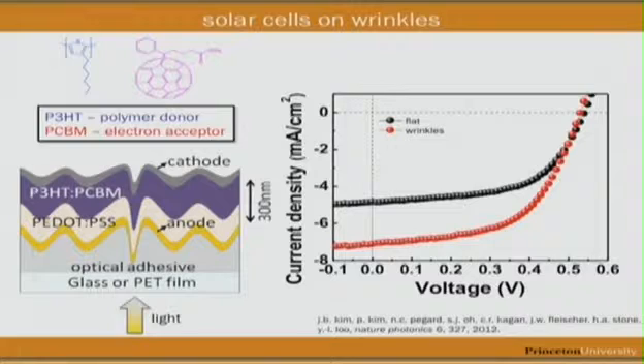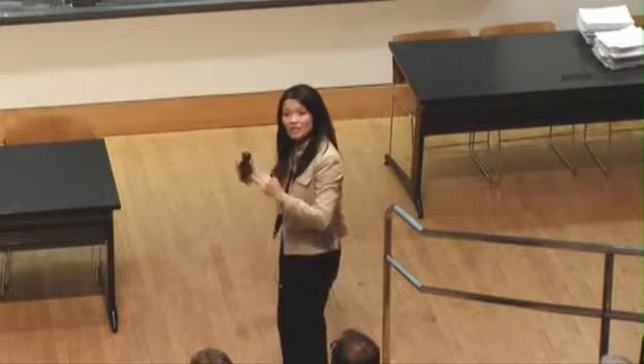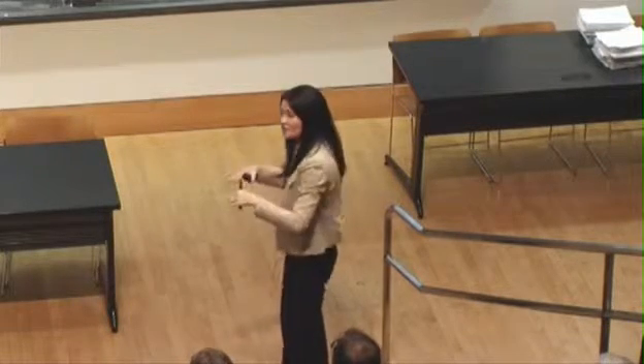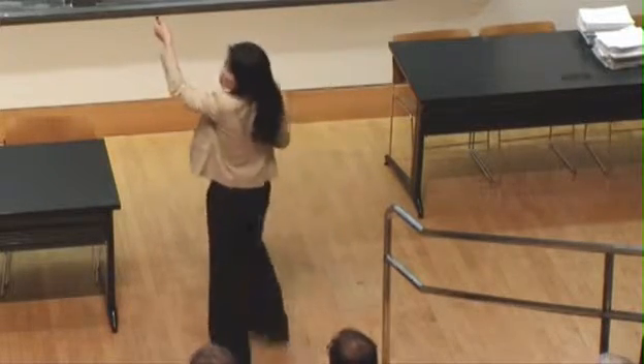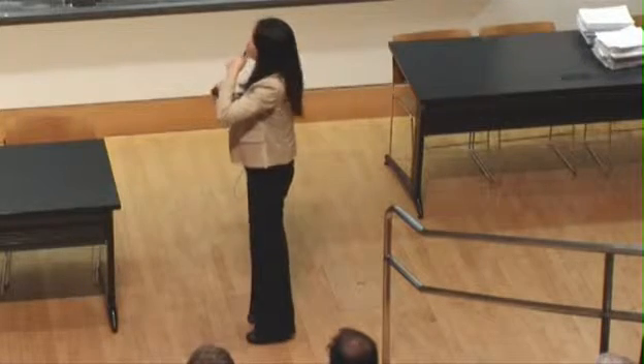If we were to make our device on a flat surface, we get this black curve. This is the power generation quadrant. It has a photocurrent of about 5 milliamps per centimeter squared. But if we make that same device on a wrinkled surface, you get this curve, so it's a bigger area now, and the current is now 7 milliamps per centimeter squared. So by just introducing the surface structure on the substrate, we've been able to boost the current generation.